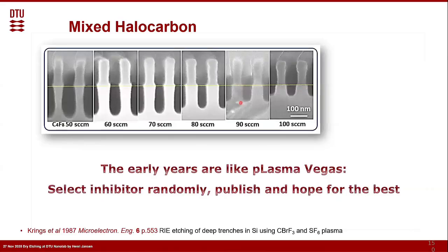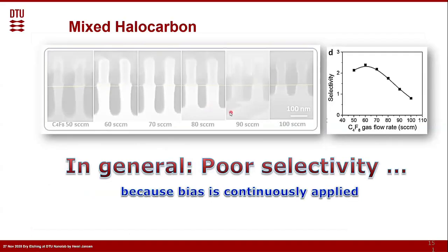Well, start with the halocarbons. So the early years, and we are talking about 40 years ago or so. What I would now call plasma Vegas: we select, a little bit randomly, an inhibitor and publish and hope for the best. So you can see that the profiles are not perfect, but it's for sure much better than at that moment, where wet chemistry was the normal one. This is, of course, much better than the isotropic results from wet etching. But in general, if you compare to state of the art, it is poor selectivity.